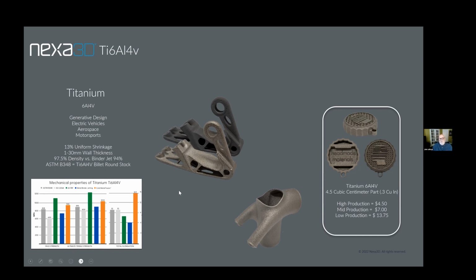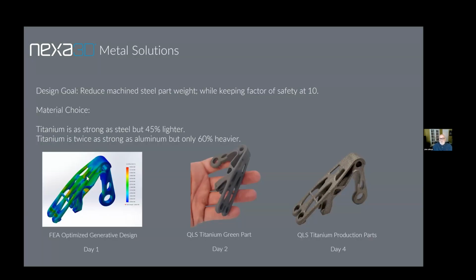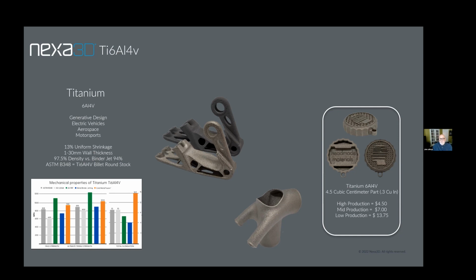You say, well, how is that possible? Well, with this system, we're using more pure feedstock than what is used when you form a round bar or a billet slab to machine. So we're starting ahead of the game in terms of the mechanical properties of the material we're working with versus machining that metal. So the way we implement that is very simple. We actually take the mechanical properties of the sintered part, which you can see here. We have better yield strength, better ultimate tensile strength, and better total elongation. We feed that data set into our FEA software, and then the result is we're going to get a part that uses less mass versus a machined part, even if we're comparing the same material. So if we were machining titanium, we're able to make a lighter part through this process than we could with titanium and retain the same factor of safety.